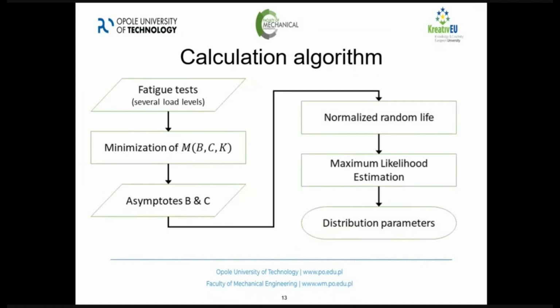So to make it more clear, here's the graph version of the model. So we have a scattered standard fatigue test. We use the minimization and get the asymptote for the standard, let's say, experimental results. Then we normalize them. We use the maximum likelihood estimation for the normalized specimens. So we get new asymptotes for the normalized version, and then we can get the distribution parameters. So basically, we normalize the results and get the size-independent fatigue life model that can take into account the size effect of the specimen.